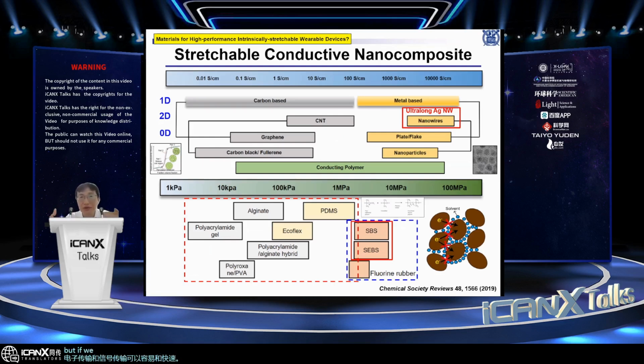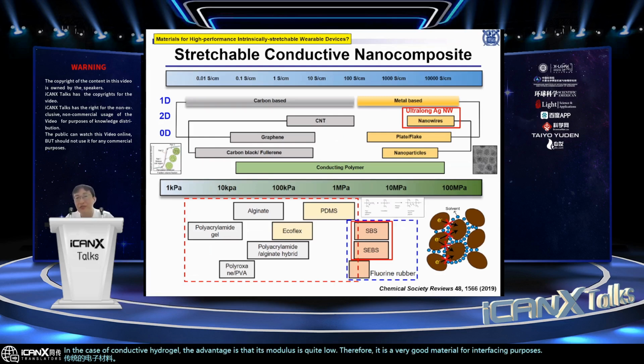But if we want to make an intrinsically stretchable wearable device, then not just the sensor part, but also the interconnection and all the materials should be intrinsically stretchable. Then that means all materials should be based on soft material like elastomer or hydrogel. That means the electrical performance of the soft material should be comparable to the conventional electronic material. And in the case of conductive hydrogel, the advantage is that its modulus is quite low. Therefore, it is a very good material for interfacing purpose, as I explained in the previous slide.